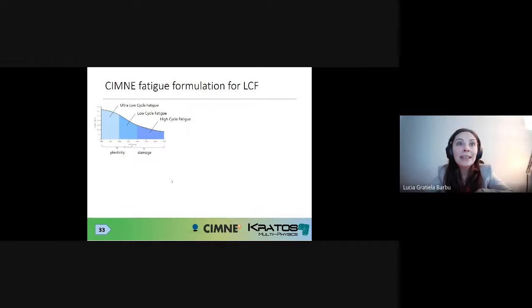Now, low cycle fatigue. Low cycle fatigue, this gray area between the plasticity and the damage domains. There is a big question that you have to answer when you're speaking about this area. And this is, if you're using a plastic damage model, which you should be using for low cycle fatigue, how much energy should you devote to plasticity and how much energy should you devote to damage?